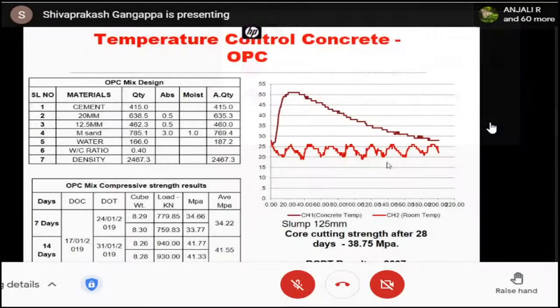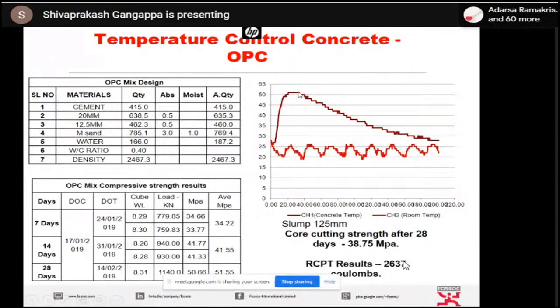temperature, and the ambient temperature is 25 to 20 for the whole day. This test was done for about 4 days. So the maximum heat of hydration, the core temperature, was 50. So the compressive strength, everything is very much perfect. At 28 days we got about 51, which was an M40 grade of concrete. We are getting about 51, perfect.